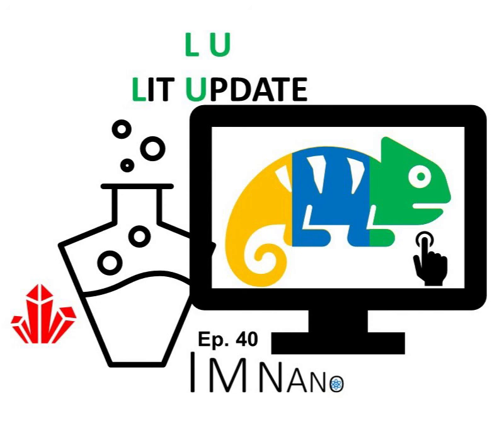E-papers, electronic paper, which is also known sometimes as electronic ink, e-ink, or electrophoretic display, are display devices that mimic the appearance of ordinary ink on paper. Yes, and the overall gist of the work is that a polar, rod-shaped liquid crystal that possesses ordinary nematic and ferroelectric nematic phases can form what is known as chiral nematic and chiral ferroelectric nematic phases when it's doped with commercially available nonpolar chiral dopants.